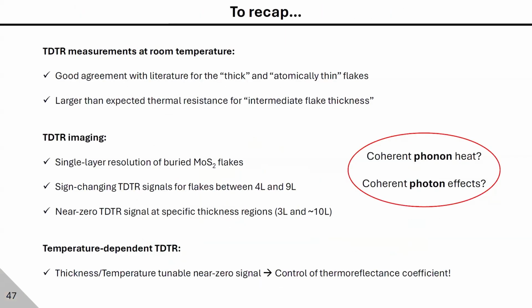So to recap, we've seen that our TDTR measurements at room temperature show good agreement with our thick and atomically thin flakes. We show that we obtain a larger than expected thermal resistance for the intermediate flake thickness. And using TDTR imaging, we obtained single layer resolution of our buried molybdenum disulfide flakes.